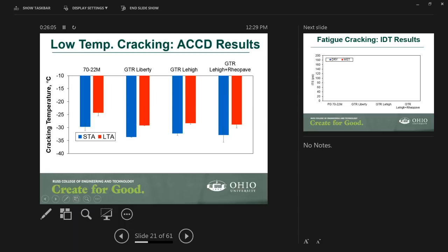So the results, as you can see here, for the long-term aging, again, once you do the aging, your low temperature cracking will drop. This is what is expected. But what we have seen is that the drop in the GTR binder was less, indicating that they might have a better low temperature cracking as compared to the polymer modified.